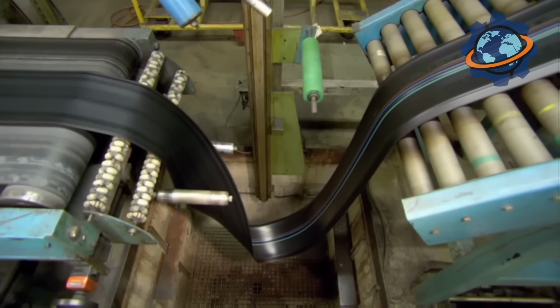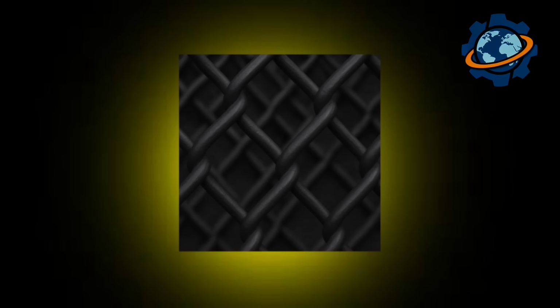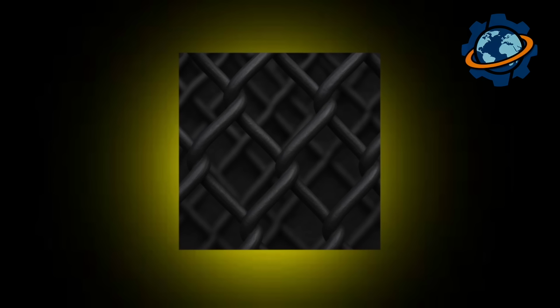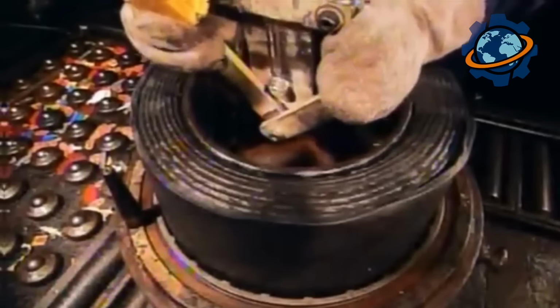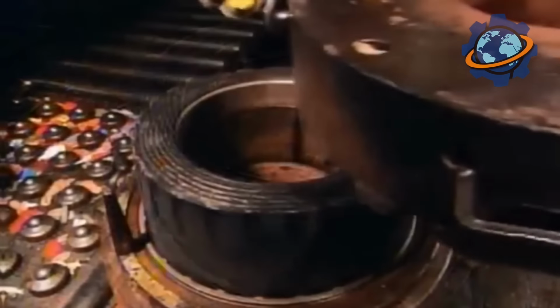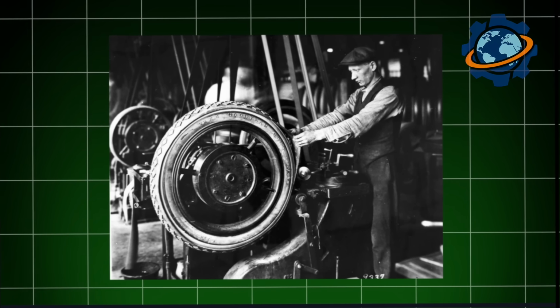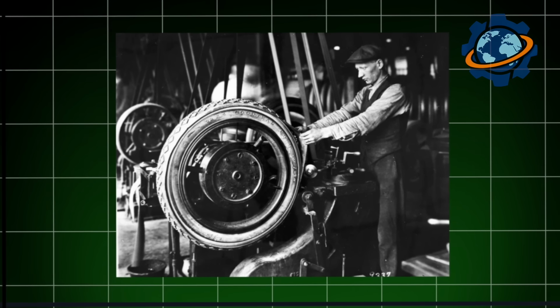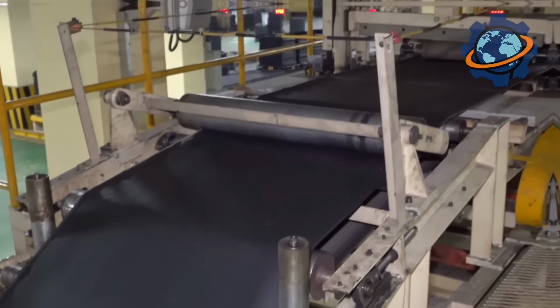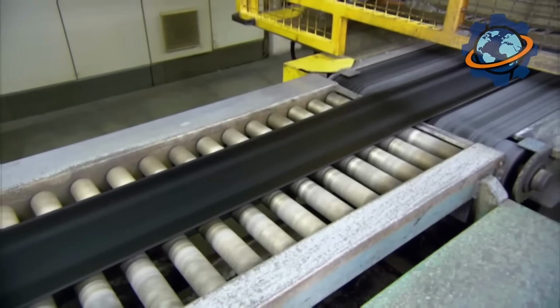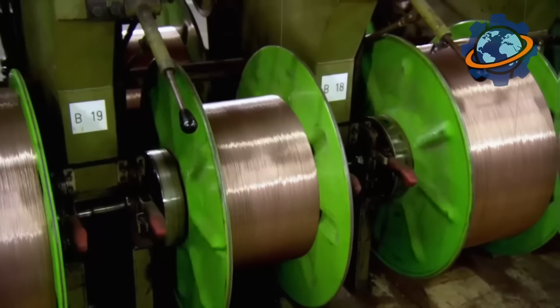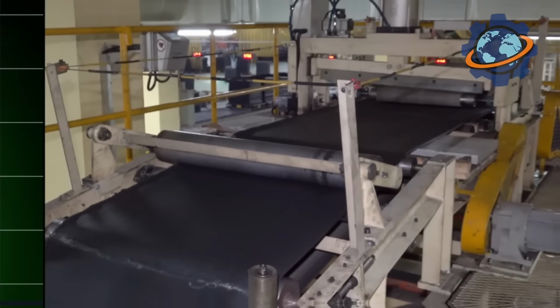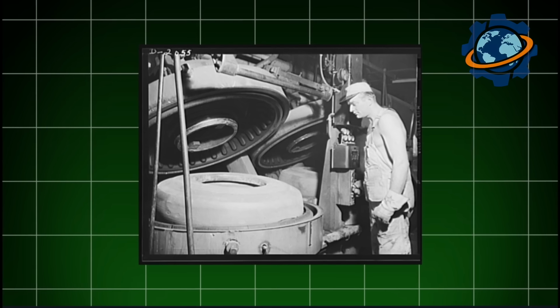Sulfur atoms cross-link rubber polymer chains, creating three-dimensional molecular networks. Picture chain-link fences welded together at every intersection. That's vulcanized rubber at molecular level. The process, discovered accidentally by Charles Goodyear in 1839, transformed useless sticky material into engineering marvel. Curing takes 12 minutes. Afterward, tires emerge rigid with crisp tread patterns and permanent shape. They'll never soften or melt again. Vulcanization is irreversible.